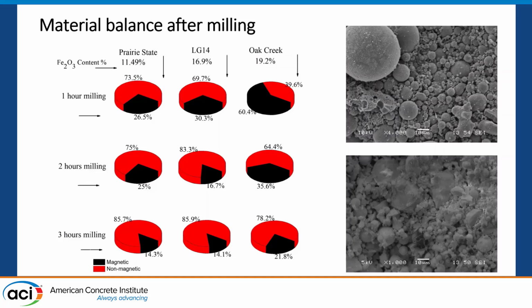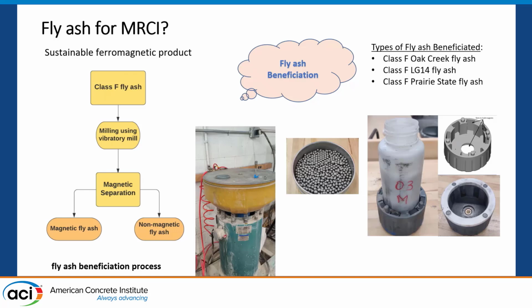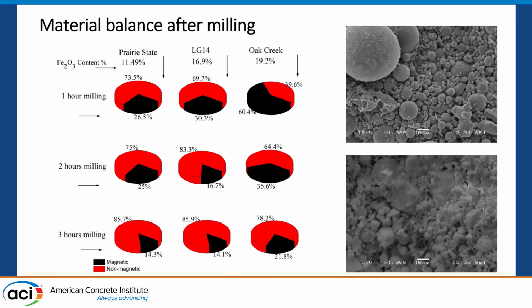So we ran milling and we ran magnetic separation. For milling, we used the vibrating mill. Normally, we use wet milling. And we would use a magnetic separator to separate the slurry of non-magnetic ash, which would, of course, contain some magnetic particles, and the perfectly magnetic ash, which would also contain reactive aluminosilicates, etc. So it's not really pure separation. But again, having two products was an extremely interesting idea for us.